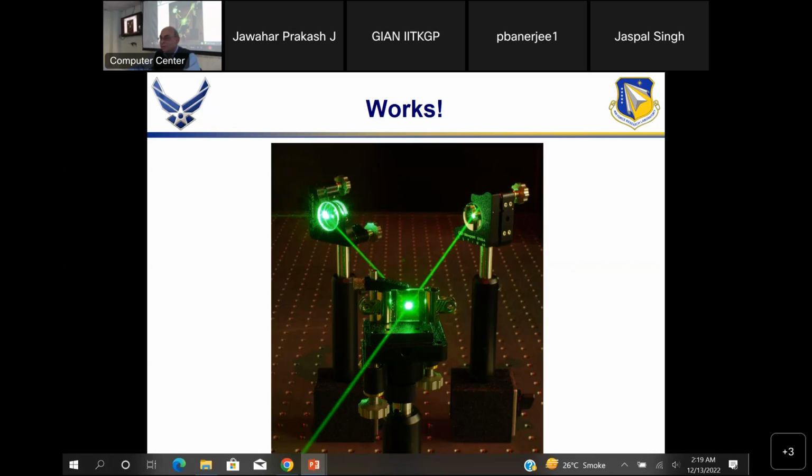Got it? These angles typically were about 30 degrees or so, 35 degrees. That is actually another good question; I'll come back to that in a second. So angle is important. Why? The effective gain coefficient of this material, meaning how much energy is transferred from the pump to the probe, depends on this angle.